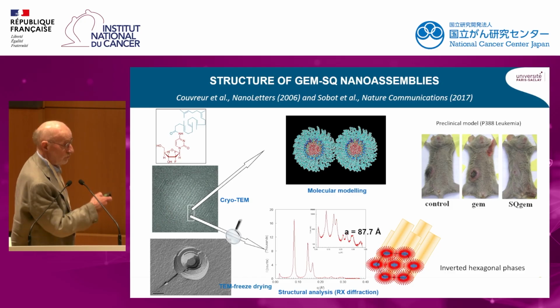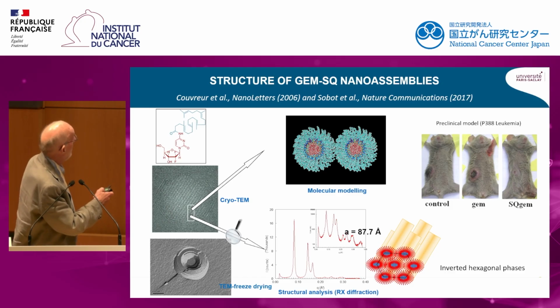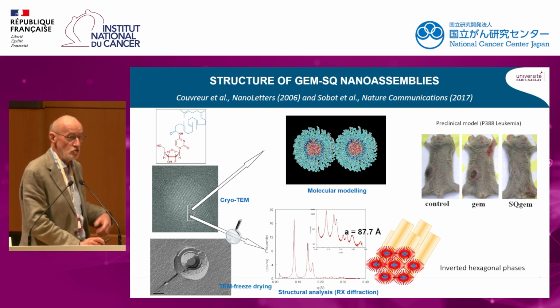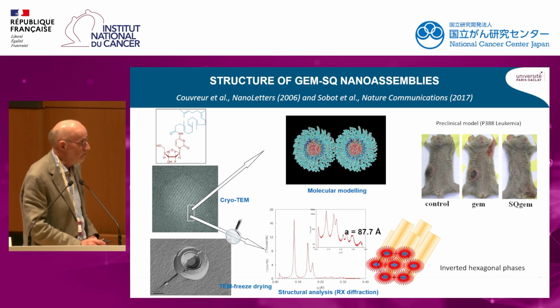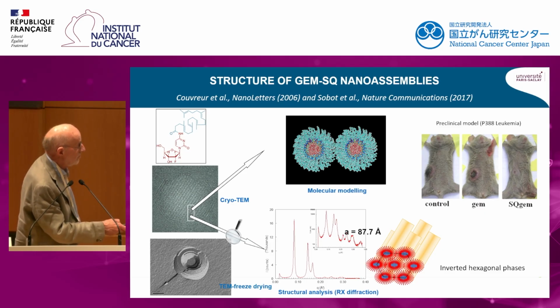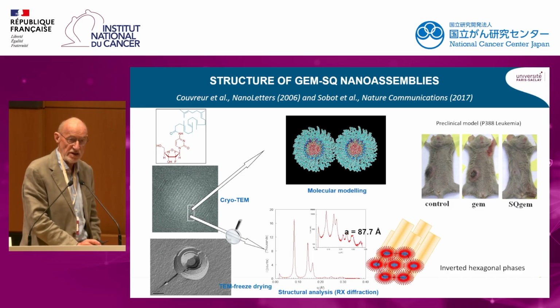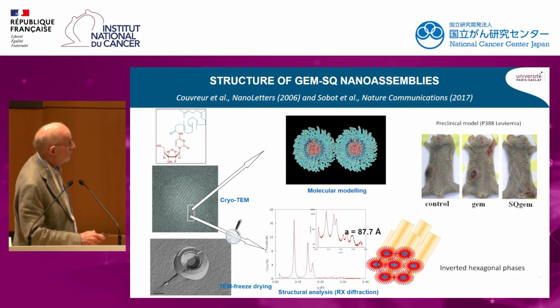The first drug that we have linked, in fact, to the squalene is gemcitabine. When you put the gemcitabine squalene prodrug into water, by cryotransmission electron microscopy, you can see the appearance of those nanoparticles with columns, which correspond, in fact, to a supramolecular organization of those molecules, corresponding to an inverted hexagonal phase that we have discovered, demonstrated by X-ray diffraction at small angle scattering.